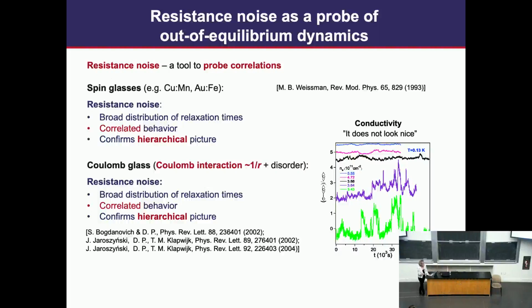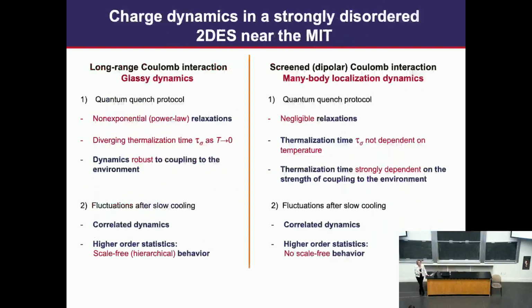So we have some unpublished data on noise in the case of a short-range interaction. The reason they're not published yet is we are waiting for our theory collaborators. This is just a summary of the differences between a glassy case and MBL. I talked about this top part - the part I will not talk about is that we studied these fluctuations obtained after cooling with a fixed carrier density. The key difference is found in higher order statistics. In the case of MBL, we do not see this kind of behavior.